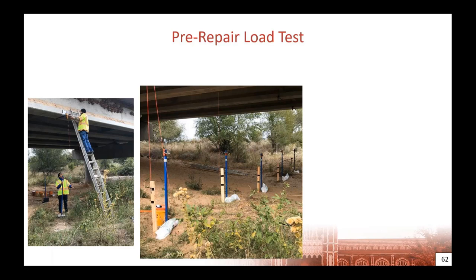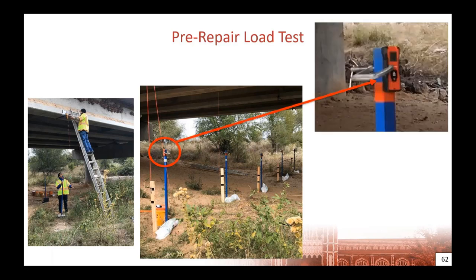And we used two methods to try to monitor deflection. The first method was using a laser distance measure that we attached to a steel pole that was stabilized with a sandbag and pointed directly to the bottom of each of the five girders across the width of the bridge. And during each load step, which I'll describe in a second, we took measurements of deflection and compared them to the non-loaded structure to see if we could monitor deflection.